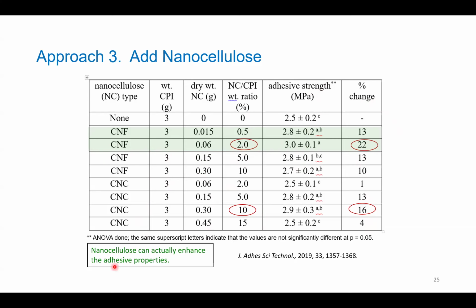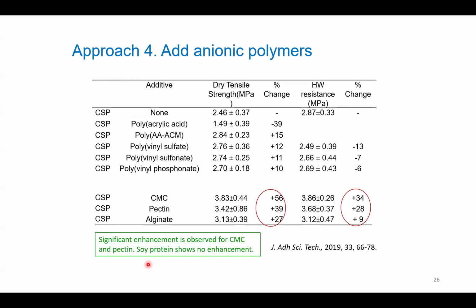So the bottom line is that nanocellulose can actually enhance adhesive performance. So here's a case where we can increase the performance as well. Now we have shown, to our surprise perhaps, that we can improve the performance even more, especially by using anionic polymer. Other additives also improve the performance, but the best additives are the anionic polysaccharides.